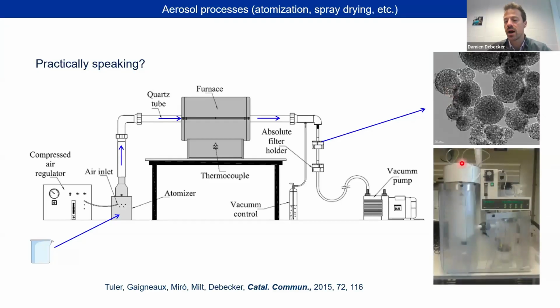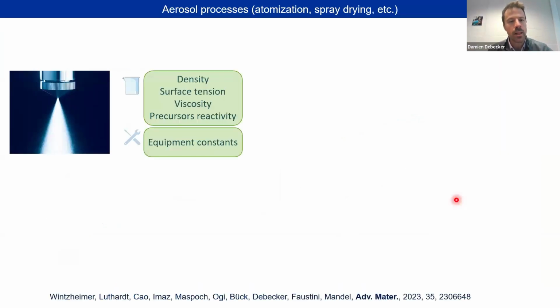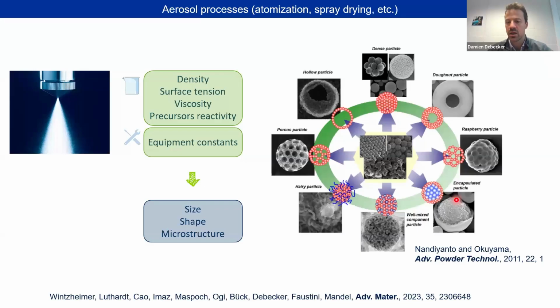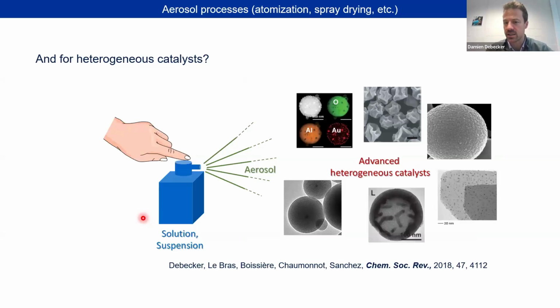Of course, if you want, you can also buy this kind of mini spray dryer that mimics what I showed you just before in the industry. And the result will be similar. It's just that you dry here under the effect of a cyclone. What is nice with those aerosol processes is that you have many parameters you can play on to finally get to your materials. I like this review, even if it starts to be a bit old. You can see here the diversity of materials you can get in terms of shape, but also, that's not visible here, in terms of composition. But you can imagine, for example, core-shell particles, porous particles, hollow particles, donut-shaped particles, etc., etc. So you can really shape your material and tailor the microstructure as well. So looking at this diversity, it's not really surprising that these kind of processes have been exploited to prepare heterogeneous catalysts, because there also you need to have a good control on the shape, on the surface, on the porosity, etc., etc.